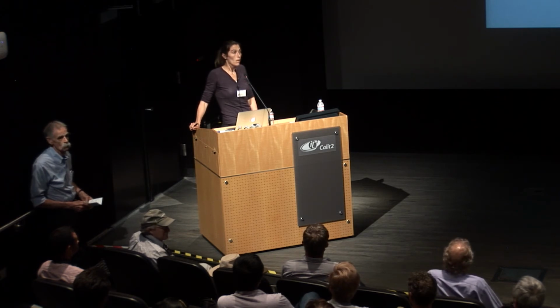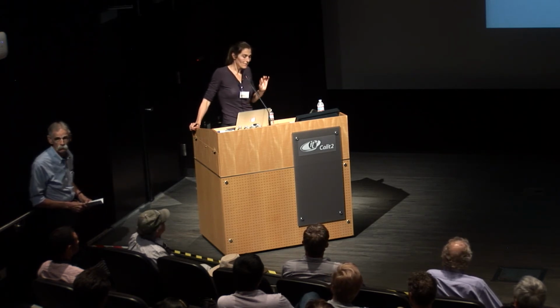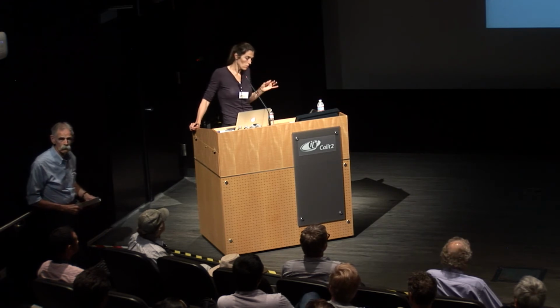I haven't talked about detecting the electrical. For the interest of brevity, I didn't talk about this, but NV centers can also detect the electric fields that are generated by these membrane potentials. It's not as sensitive an electric field detector, and one loses a little bit by the Debye screening. If your NV center is outside of your neuron, the electric fields die off quickly. Magnetic fields don't die off as quickly because they don't have this extra Debye screening.